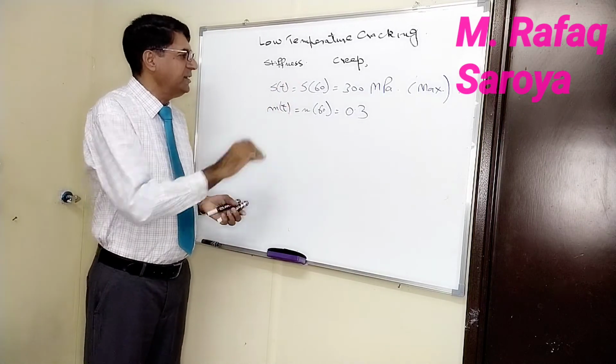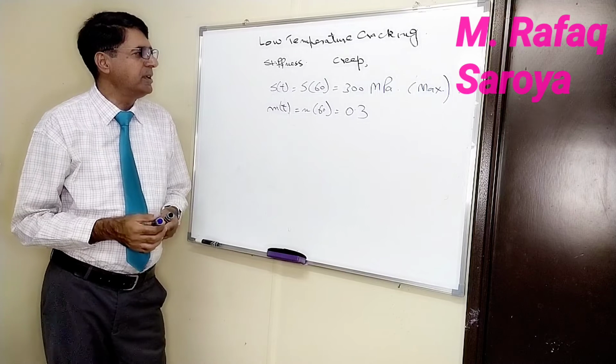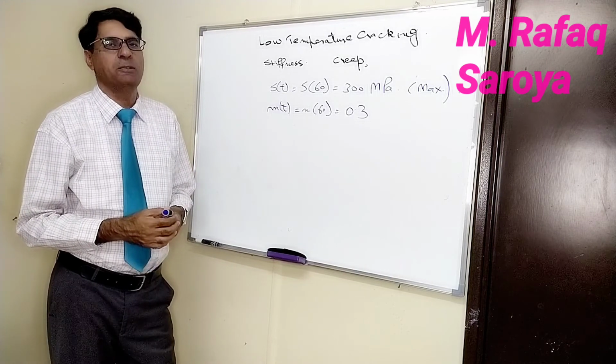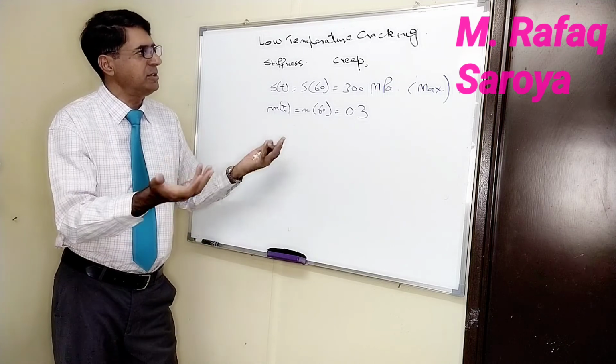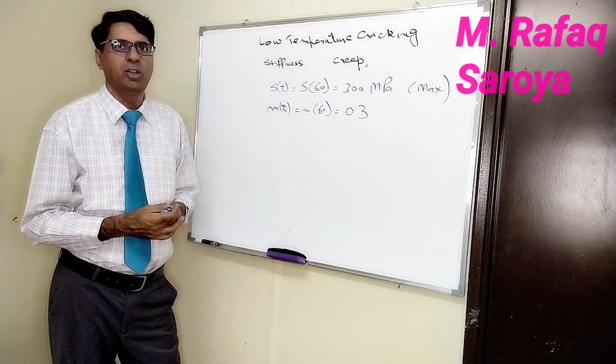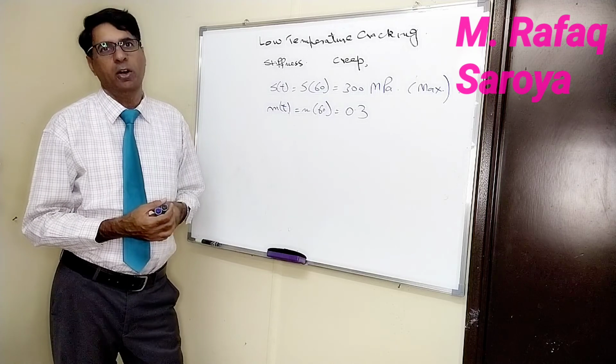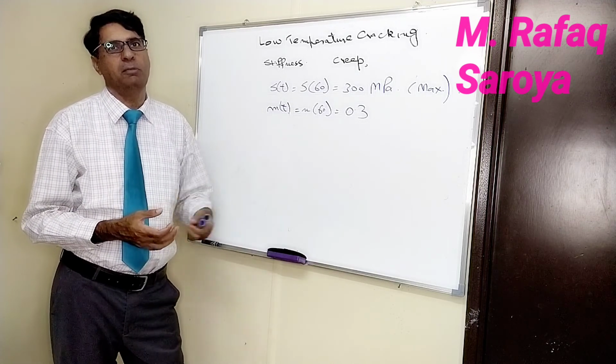And now, this test is always performed by the bending beam rheometer test, BBR test. Bending beam rheometer test. And the temperature, as I have already given you, is minus 12. How this minus 12 Celsius comes, I have given you in the calculation.